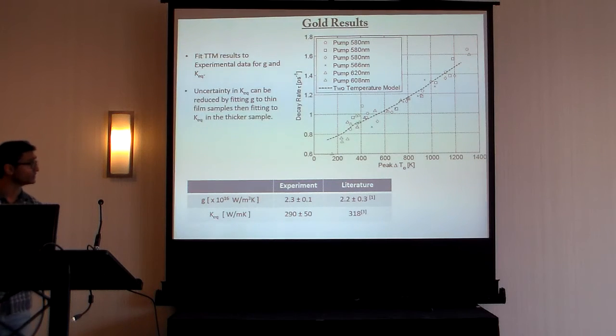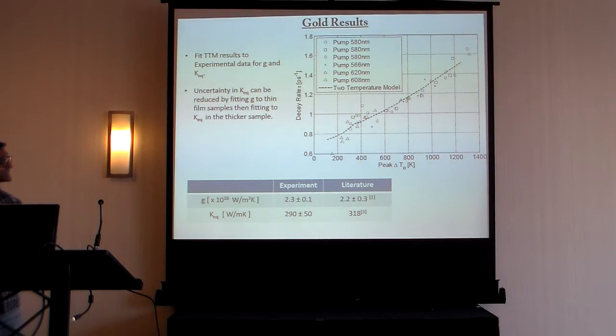So here are results for gold. The markers indicate experiment data for a range of pump wavelengths. The y-axis is the decay rate, and the x-axis is the peak change in electron temperature. Varying values of G and K in our model, we can find the best fit results, and we found that the values of G and K correspond very well with literature values.